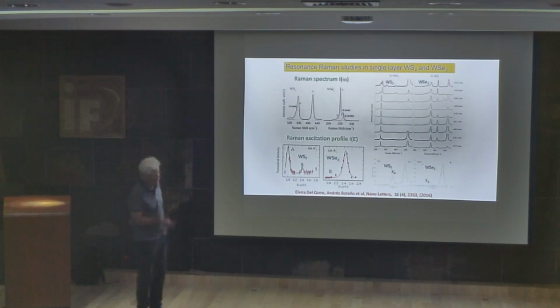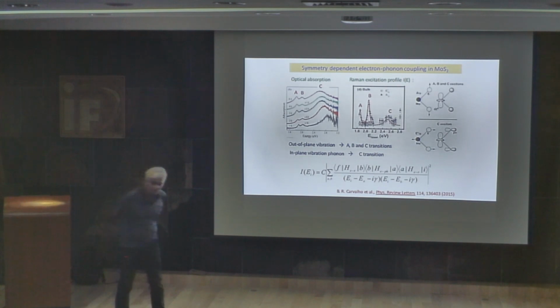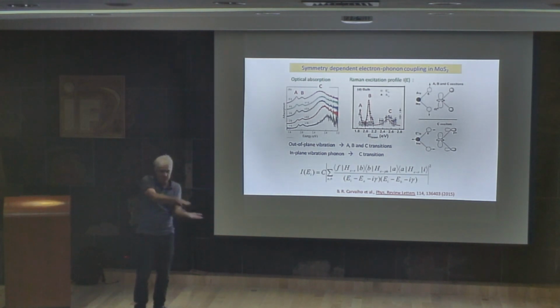Okay, then what does the lifetime of the excitons depend on? The lifetime of the exciton. I think that mostly it probably relates to the presence of defects or the environment, because the excitons are very strongly influenced by the environment. The substrate, depending on whether the sample is suspended or on top of a different kind of substrate, because the electric fields go into the substrate. The widths are very much dependent on that, that's right.